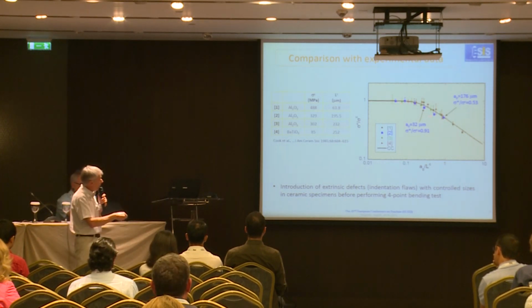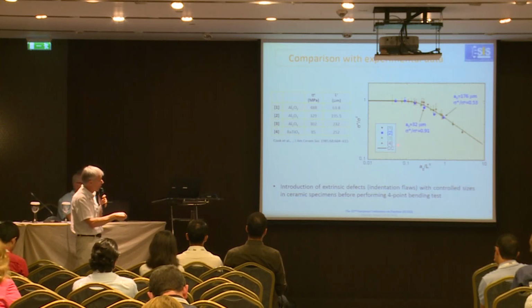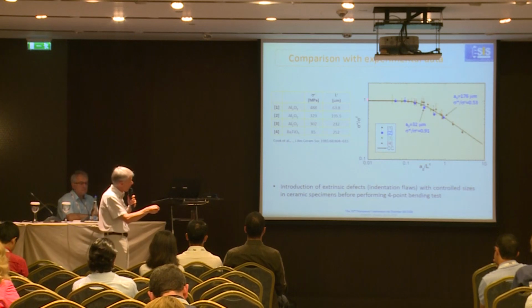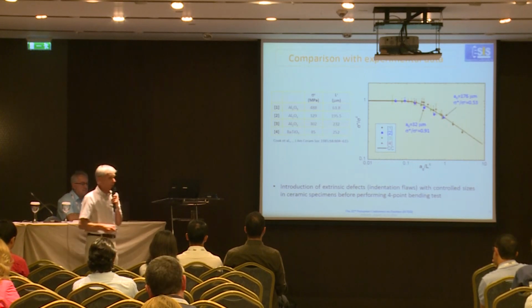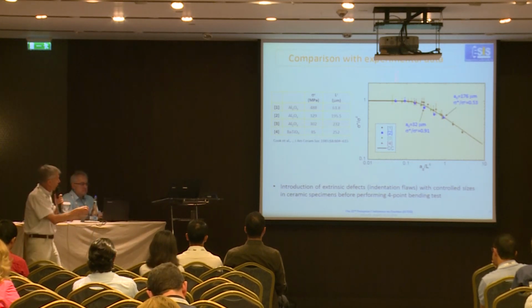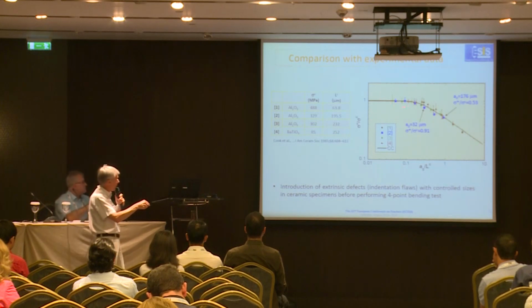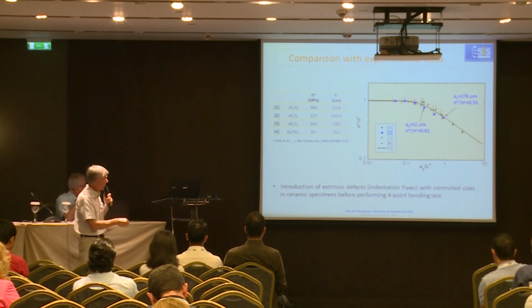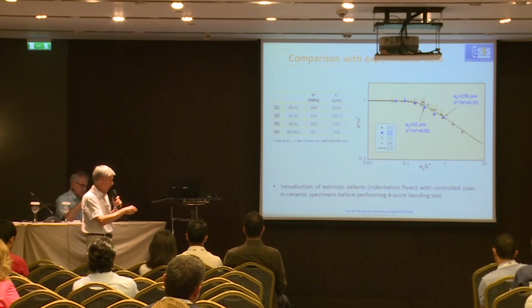And if I use the coupled criterion for a sharp defect in this case, I get a quite good agreement with those experimental data. So it is interesting to see that we have this plateau as predicted by the coupled criterion.